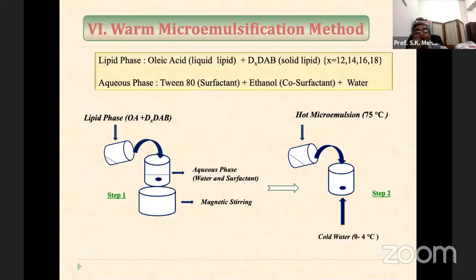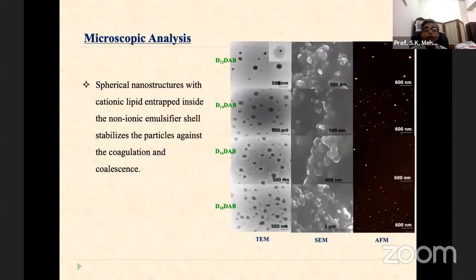We also used, a few years back, this warm microemulsion method to create solid lipid nanoparticles, where we use oleic acid as lipid base, which is a liquid lipid, and the solid lipid we use is the surfactant DDAB, which we can range 12, 14, 16, 18, all types are available. And the aqueous phase is Tween 80, again very much acceptable from a biological point of view, ethanol, water. So we prepare the lipid phase, we prepare the aqueous phase, and we mix them. We call this hot microemulsion method, where we keep 75 degrees temperature, and then we use cold water at 0 to 4 degrees. And using these two steps, we can create solid lipid nanoparticles.